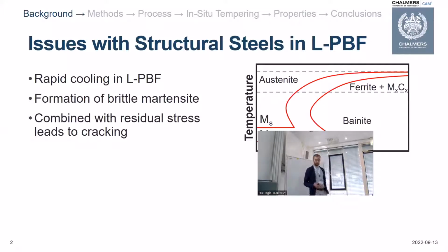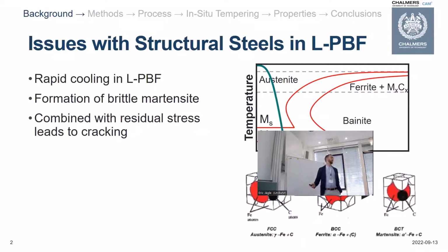Now, currently, the use of structural steels in LPBF is quite limited, and this stems from the relatively high carbon content of these alloys. This carbon content leads to an issue with processability because the carbon within your cooling austenitic phase has insufficient time to diffuse and form carbides due to the rapid cooling conditions that you have. So what happens instead is, as you have your rapid cooling, the carbon within your austenite becomes entrapped at octahedral sites of your FCC austenite lattice and induces the transformation to the distorted BCT structure of martensite. Now, this martensitic phase is very hard and brittle and creates material that's highly susceptible to fracturing.